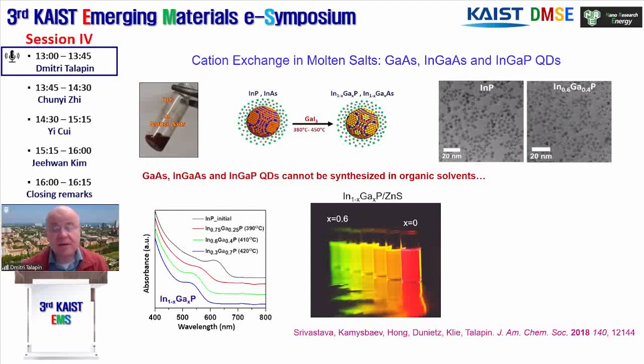using traditional organic chemistry. But in molten salts, all these problems kind of magically disappeared, and we could go to higher temperatures. We could go to pure oxygen-free environments, pure C-H-free environments, and in the first generation of methods, we started with indium phosphide quantum dots, for example, and did cation exchange to make indium gallium phosphide. And we could fully cover the space from pure indium phosphide to gallium phosphide.